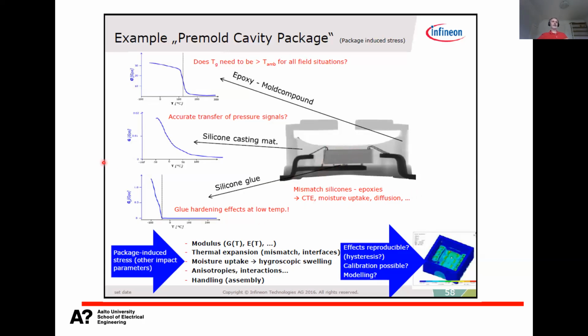So now when you think that you would need to analyze the stresses, and based on the stresses, the reliability for certain use conditions, you need to see that in different temperatures, different materials behave differently. And then if you want to accelerate the test conditions, then you need to be sure that, for example, if the use temperature is -20 to 80, then in the acceleration testing, you cannot go to -40 if this is -30, because then your material would behave completely differently.